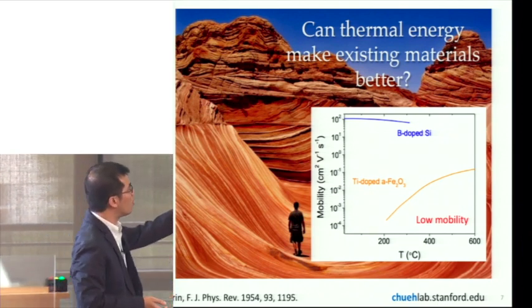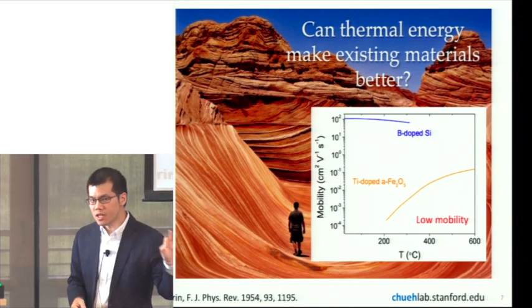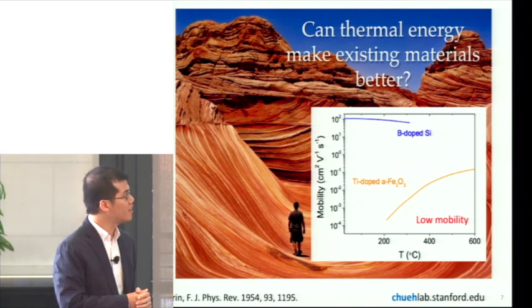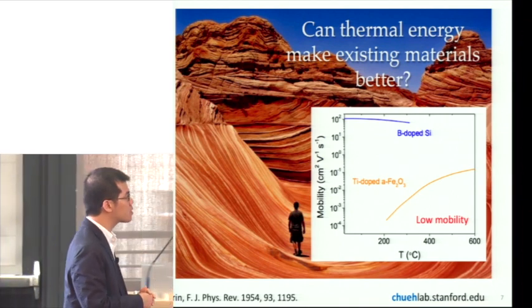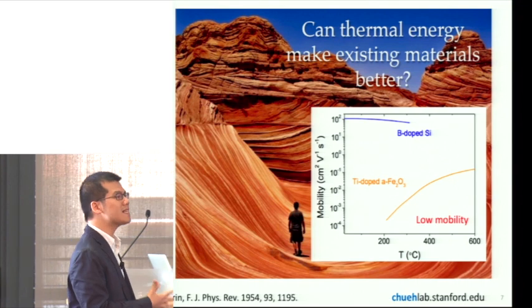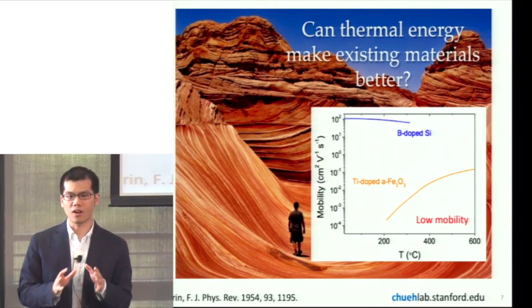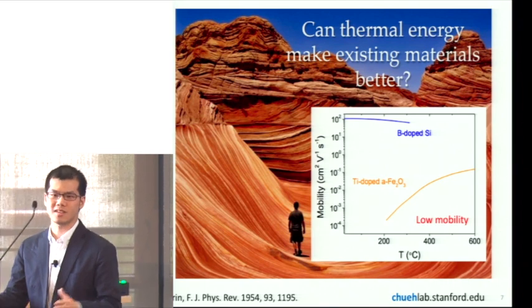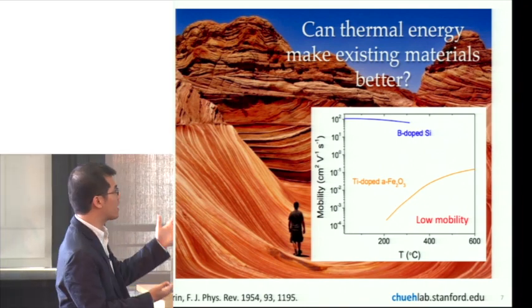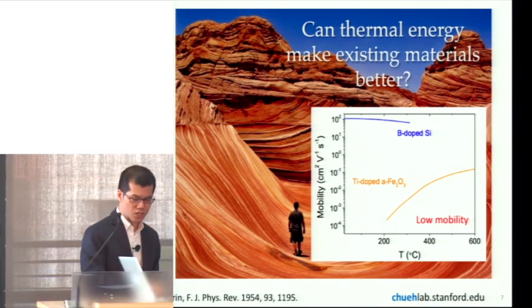One of the big problems with many of these earth-abundant materials is that electrons don't travel very efficiently in them. In a material like iron oxide — a close relative of rust — the electrons are so immobile that it's impossible to measure how fast they travel at room temperature. In contrast, silicon, used in current solar cells, has electron mobility that is 10 orders of magnitude higher than iron oxide. Yet we have been trying to deploy iron oxide to absorb sunlight and use the photo-excited electrons to dissociate water into hydrogen and oxygen. As you increase the temperature of your solar cell and photoelectrochemical cell, the mobility of the electron actually increases exponentially — by about six orders of magnitude going from room temperature to 400°C. Thermal energy therefore represents a possible mechanism to enhance performance, though the current paradigm says that increasing temperature reduces the open-circuit voltage.